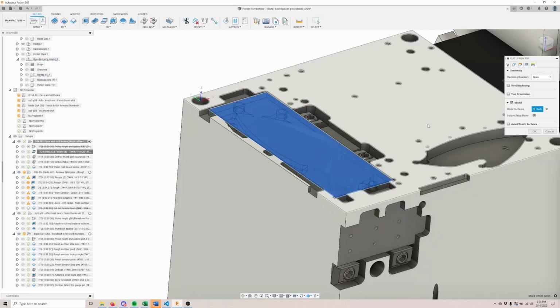I'm leaving like 7/8 thou, just because the process still isn't perfected, if you will, surface grinding wise. So if there's any warp or a really bad bow or something in the part after heat treat, you need enough material to actually be able to surface grind that warp or bow out. So that's why I'm leaving a lot. In the future, I'd like to only leave like 5 thou, because that would increase the surface grinding speed significantly.